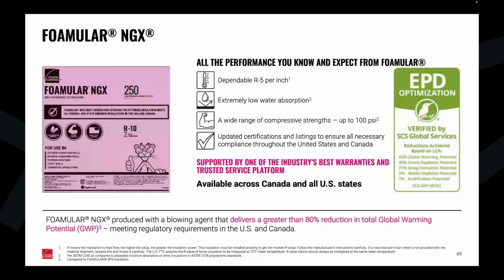Jumping into Foamular NGX and this special product. We're very proud that we were the first to come out with the next generation, if you will, of extruded polystyrene insulation back in 2020. It was kind of a race to the finish line to make that happen. And we wanted to make sure that we didn't trade in the performance in all of the other categories, even though we were trying to lower the global warming potential of the material. So we still have that R5 per inch thickness. We still have the high water absorption resistance, very high compressive strength up to 100 PSI, and additional certifications. As you can see here, we've got an EPD optimization as a result of the efforts that we put in.